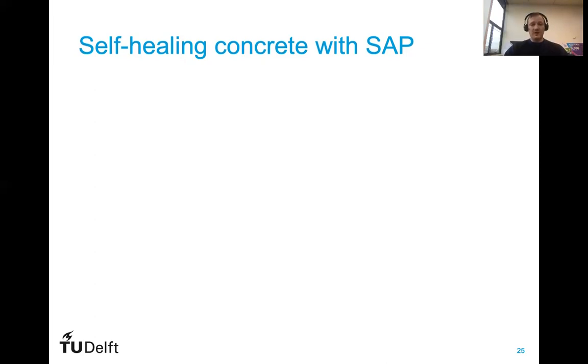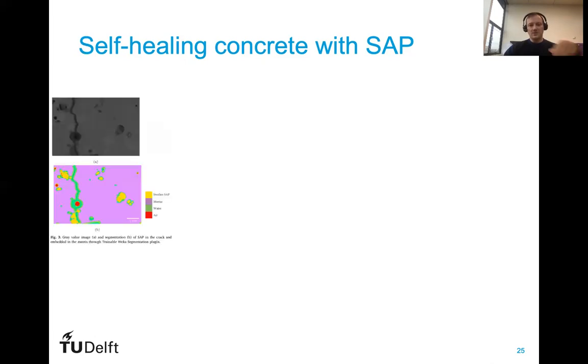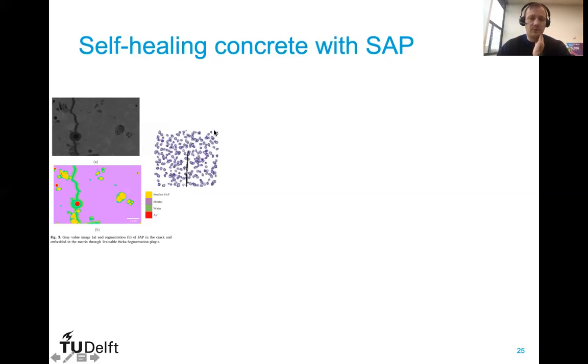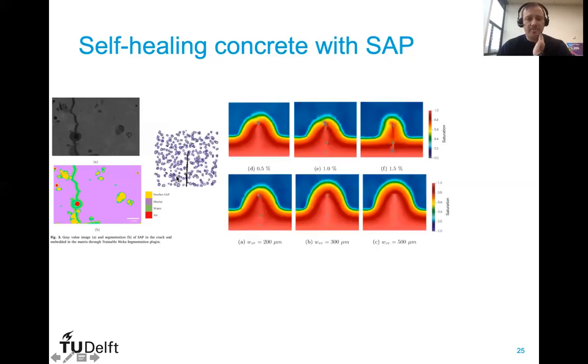We have recently also developed a numerical model within the Lattice modeling framework that can help us design self-healing concretes with superabsorbent polymers. So again, here we can also see what happens in experiments, that we have swelling of SAP particles under exposure of water and formation of macropores if that happens at an early stage. So this SAP particle needs to swell in order to block the transport of water, possibly containing harmful species, inside of the cementitious matrix. We can also simulate that. We pack SAP particles inside of a box, and then we simulate the cracking process. After that, we can simulate the healing process and the penetration of moisture.